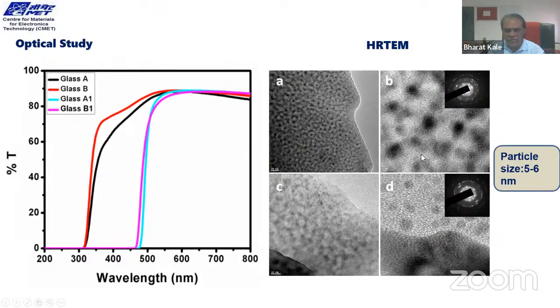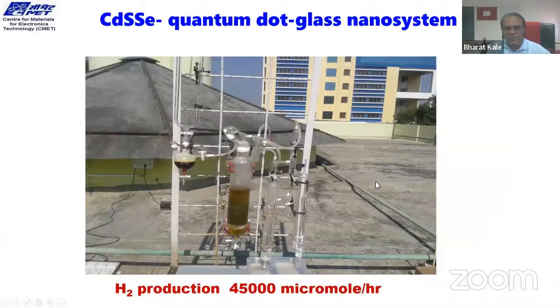You can see very uniform quantum dots. Then we also ran a pilot plant for hydrogen production using our glass system. And we produced hydrogen at 45,000 micromole per hour. It's almost 2 liters per hour of hydrogen evolution observed when we use cadmium sulfide quantum dot glass nanosystems.